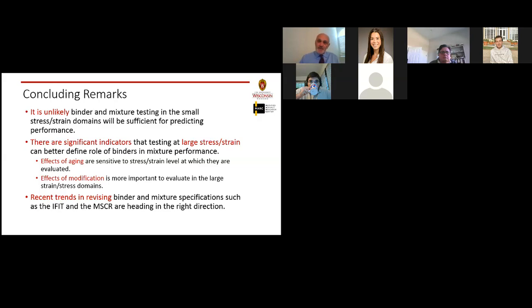So in a short answer, steady state creep needs to be established, whether it's mixtures or binders. And if you look at the data you have for rutting in the Hamburg, isolate the moisture damage, you will find the steady state creep rate very clearly in most of these mixes. Thank you.